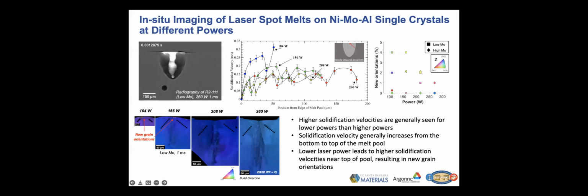We can then couple this with post-mortem characterization. Here we're polishing into the center line of the melt pool. We can see for the higher power conditions, in this case, we're able to retain the substrate orientation. Why is this important? If we want to create highly oriented crystals for applications like nickel-based superalloy turbine blades, we actually want to promote anisotropy, and we want to promote the retention of the substrate orientation. We see, however, at the low power conditions that at the tops of the melt pools, where the highest velocities are experienced, we tend to see new grain orientations form.